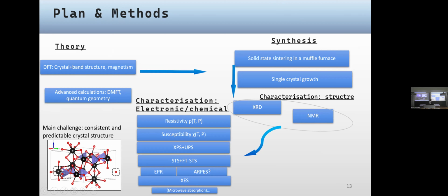Those are in the hexagonal symmetry. The nomenclature is 4f and 6h Wyckoff positions, and only the 4f is considered of importance for those kinds of applications. So there is a problem of controlling exactly the stoichiometry and the crystallographic positions of the doping atoms. That's why it's highly required to come up with more predictable synthesis methods than were already used in the literature. But as well, there are ways to tune those distributions chemically by replacing one or the other constituents.